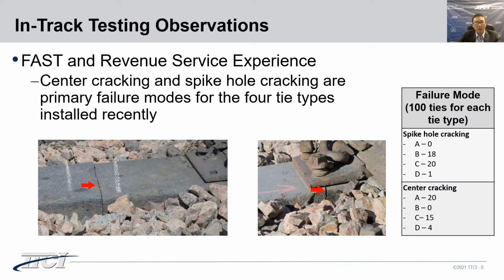tons. However, there are a couple of failure modes associated with composite ties that are typically not seen on wood ties. Center cracking, which was not observed during installation, has been observed on at least 3 different composite ties in recent testing at FAST. This test at FAST showed about 10% of composite ties experienced center cracking within 200 million gross tons (mgt) of heavy axle load traffic.